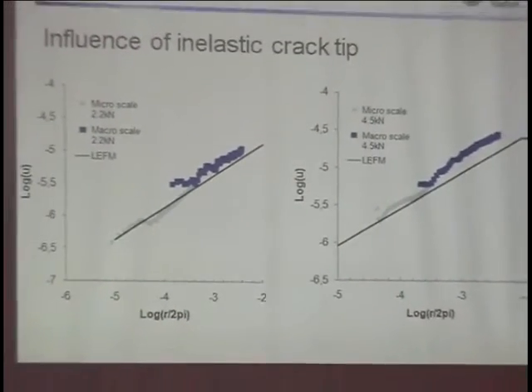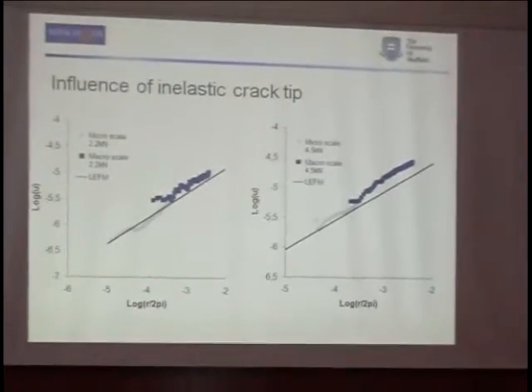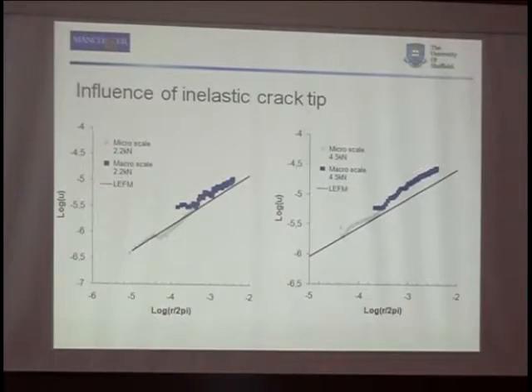And this is what David was plotting just now, basically log U against log R. And you see that at 2.2 kilonewtons you get quite good agreement, whereas for the 4.5 one, where there's significant plasticity, you get this deviation from the theory. What we will be doing in the future is to plot it at different angles as opposed to just at theta equals 0. And we suspect where the characteristics of the two plastic lobes are, we'll probably get significant deviation from that.